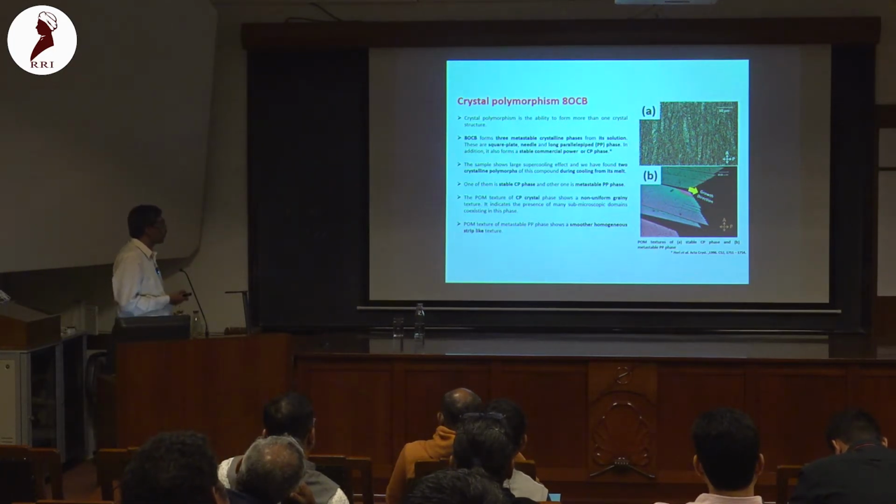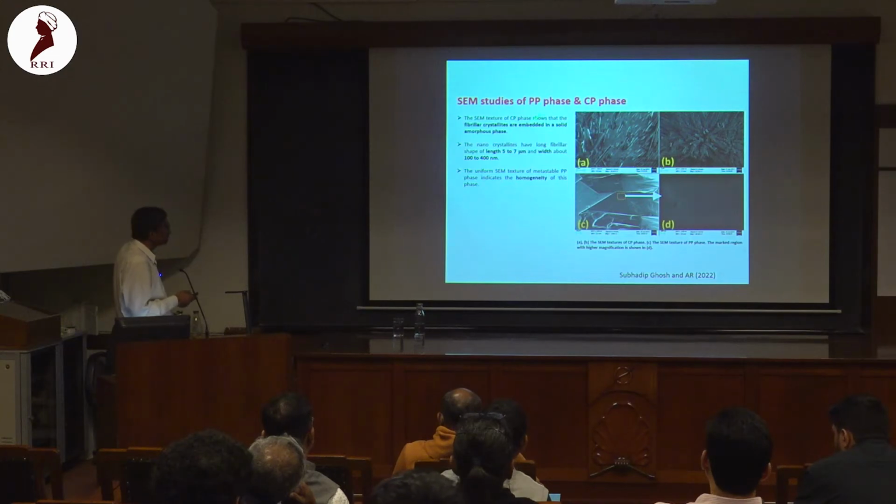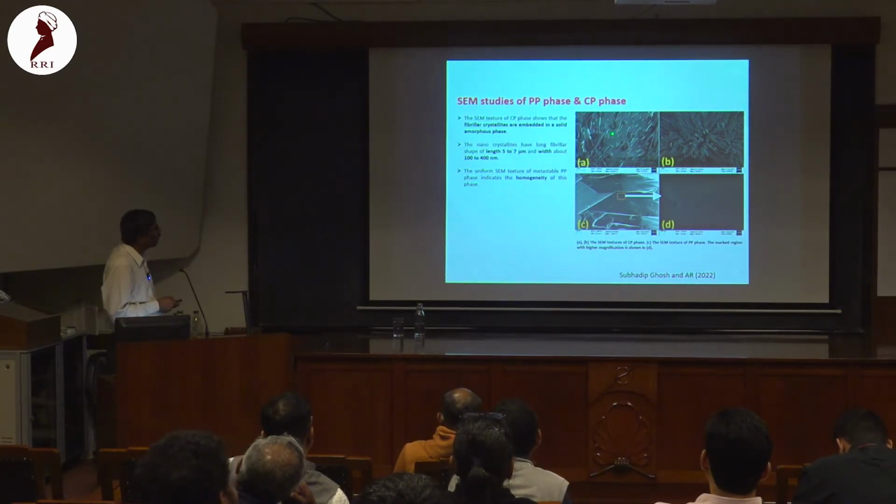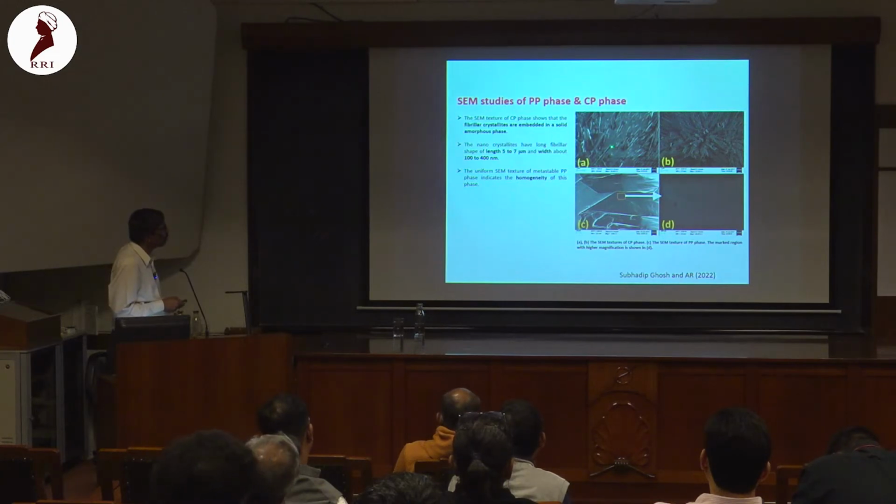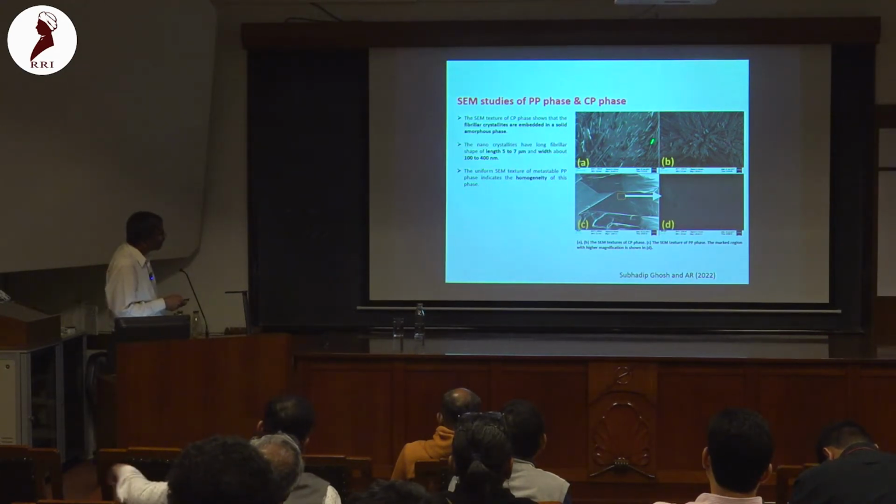in the liquid. Now when we studied this CP phase with SEM studies, you will see that the CP phase is not actually a homogeneous phase. There are lots of fibrillar crystals inside, and between the crystals there is some kind of amorphous phase. So this is a coexistence of these two phases in the CP phase.